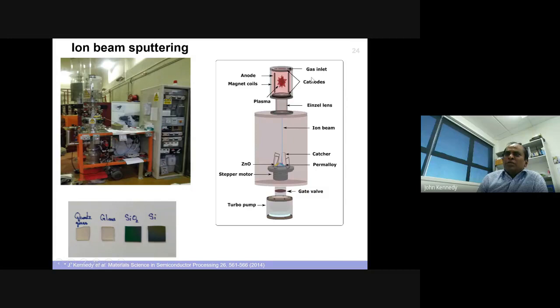The ion beam is generated from an ion source. It's a simple RF ion source. You have an anode and cathode. You form an RF plasma. Then you generate, let's say, a milliamp current. You hit that target. You sputter them. Then you have a substrate as a catcher. You catch it as a film.